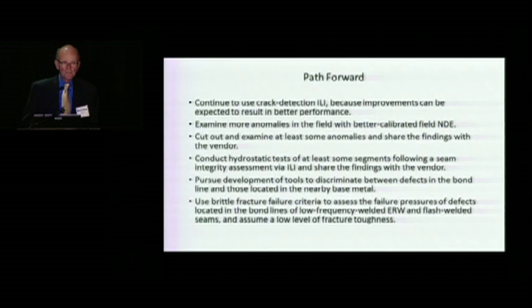So things do evolve, and I'm confident that we will see improvements to the point where we will have the confidence where we don't have to do hydrostatic testing. And we don't want to do that because you have to take the pipeline out of service. It's not good for short, deep defects. Those can leak shortly after a test.